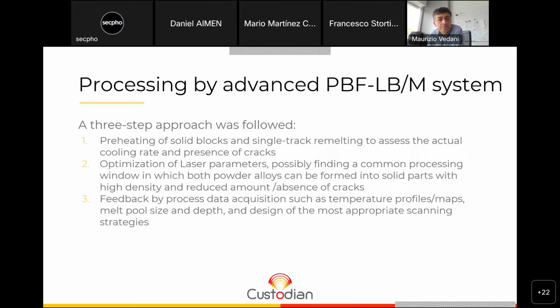On the other hand, a process parameter optimization was carried out for both materials, for the CM247 low carbon and the Inconel 713 low carbon, with the standard setup. So with no preheating, no custom beams, just with a common Gaussian distribution beam of a standard PBF process, with the aim of finding the processing conditions where these powder alloys can be formed into solid parts with high density and with a reduced amount of cracks. And last but not least, we got plenty of process feedback as temperature profiles and the melt pool size, as melt pool depth and width, and we designed the most appropriate scanning strategies where we can carry out the powder bed fusion experiments.